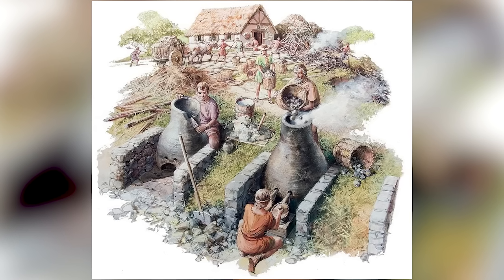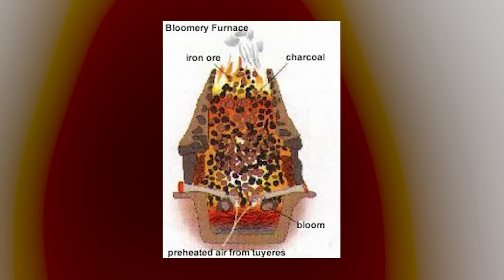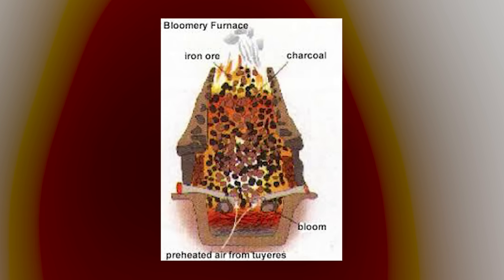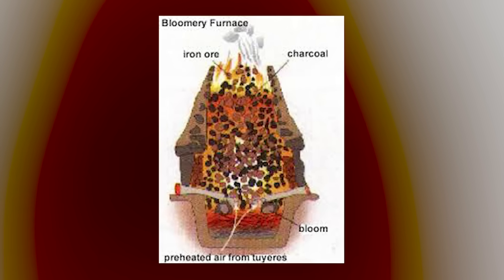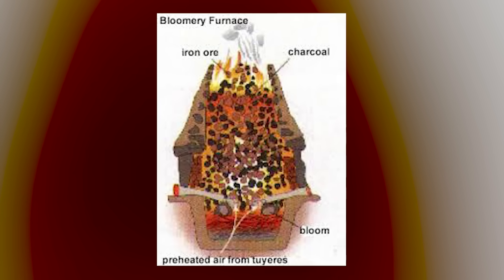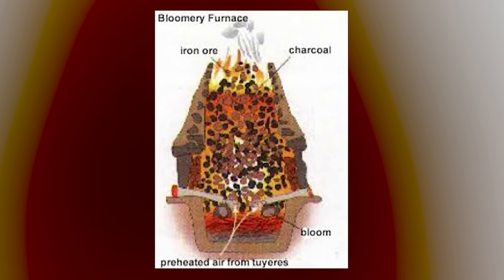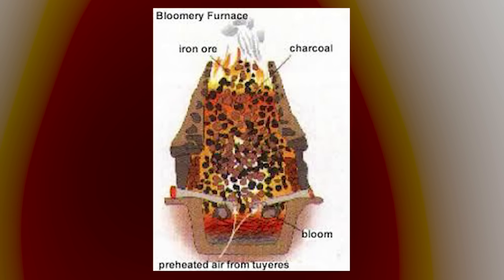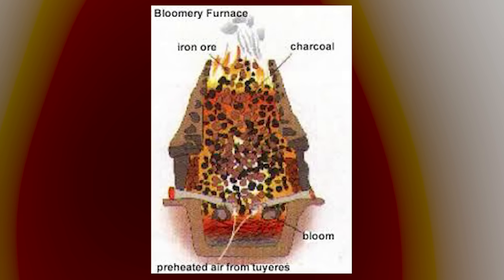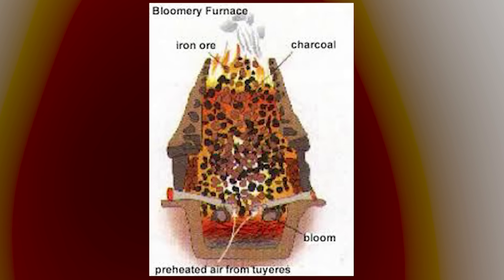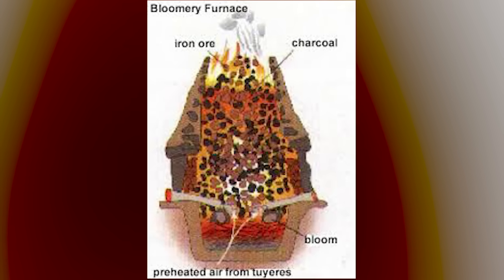Here is where the magic happened. As the iron particles were forming, surrounded by burning charcoal for hours, they absorbed carbon unevenly. Some areas absorbed very little, staying as soft wrought iron. Other areas absorbed more, accidentally becoming steel. And all throughout this mess were threads of that protective slag.